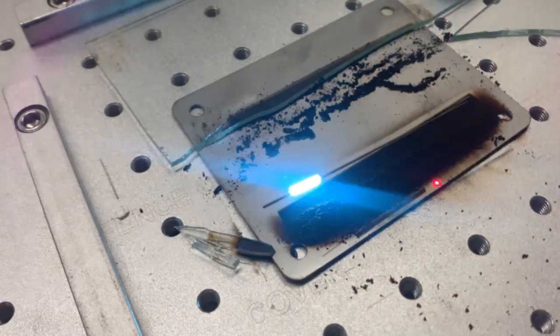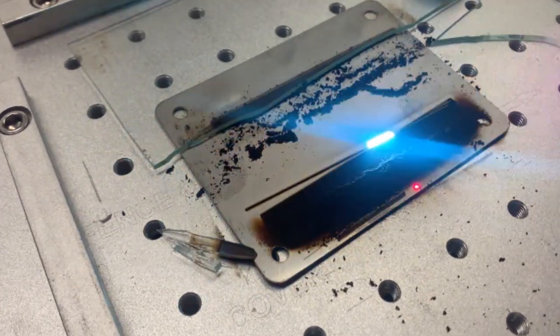Whoa, how's that? The metal got so hot the glass fractured. I guess that wasn't so much of a surprise given the amount of heat going into that stainless steel. So I've rethought the experiment. I don't need to do it all that dense. What I'll do is just keep lasering over and over a little patch so it doesn't heat up the glass.